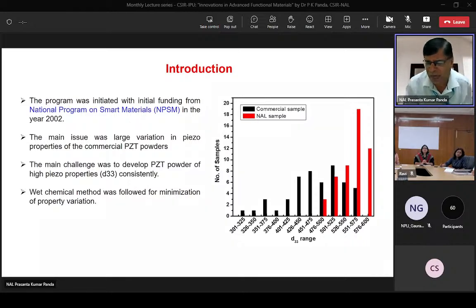As you can see from the graph, at that time in 2002, commercial samples were showing large variation in properties, from 300 to 550 picocoulomb per Newton, while the material we prepared at NAL was showing a minimum of 500, and a narrow band of properties is achieved. I'll come to the details in the presentation thereafter.